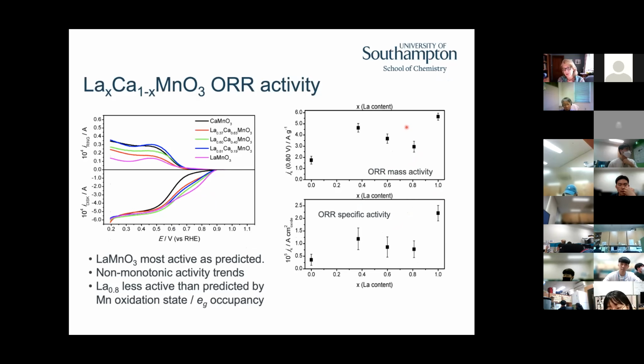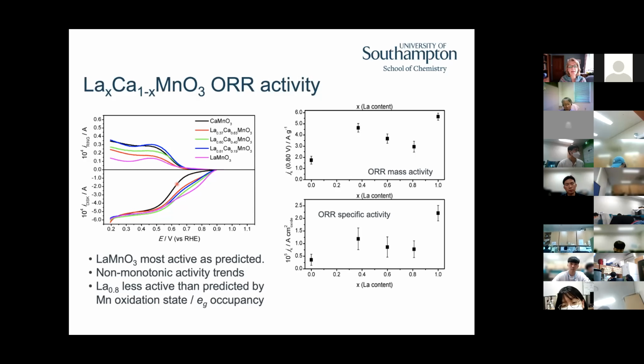Let's look at the oxygen reduction activity, and this is the rotating ring disk experiment. So here is the disk where we're reducing the oxygen, but the products then travel out to the ring and we can oxidize those. And we can see that the calcium manganate turns on at the most negative potential. It's the least active material. And as soon as this oxygen reduction turns on, the peroxide formation also turns on. So this is the oxidation of the peroxide.